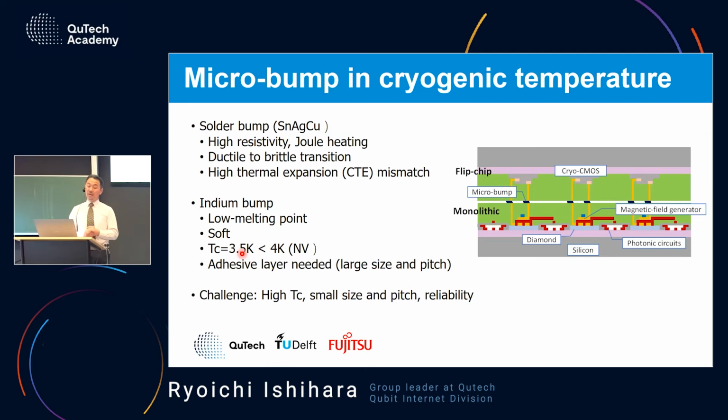And to bond between indium, we need an adhesive layer. Again, the additional adhesive layer limits alignment accuracy or increases bump size. So in summary, the challenges in microbump in cryogenic are high Tc, small size, fine pitch, and high reliability.